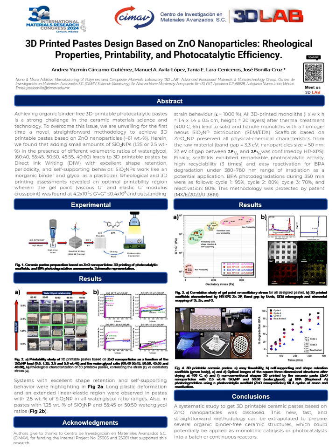Everyone, in this work entitled 3D Printed Paste Design Based on Zinc Oxide Nanoparticles: Rheological Properties, Printability, and Photocatalytic Efficiency, we present for the first time a novel and simple methodology to achieve 3D printable pastes based on zinc oxide nanoparticles, 61% by weight. Here we find that the addition of small amounts of silicon oxide nanoparticles, 1.25% or 2.5%,